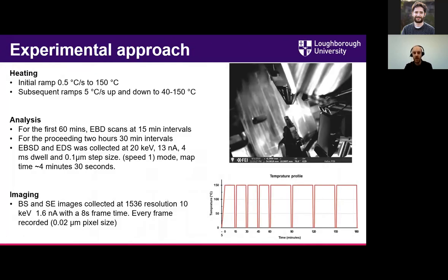So once we've taken that, we put it on the hot stage, and then we had a simple experiment where we heated the sample up at half a degree a second up to 150 degrees, and this was our thermal aging temperature. And then we cycled it up and down doing analysis once we'd cooled it down. And we did a coarse sampling to start with and sparse sampling later on. So we did EBSD scans every 15 minutes for the first hour. And then for the subsequent time, we just did EBSD every 30 minutes. So this is one of the issues with these. It's a relatively time-consuming process, but it's a better option sometimes than making an individual sample for each thermal aging condition.